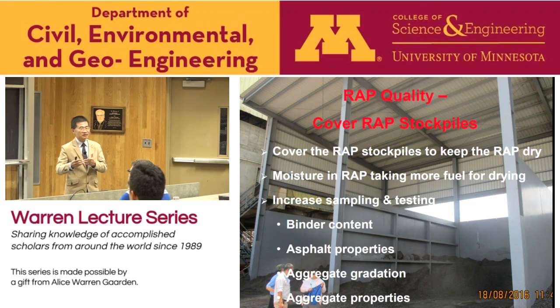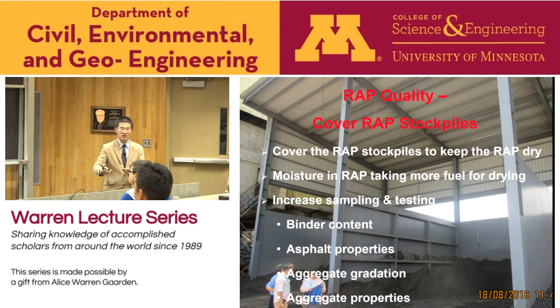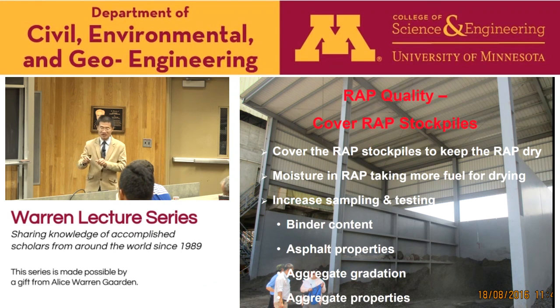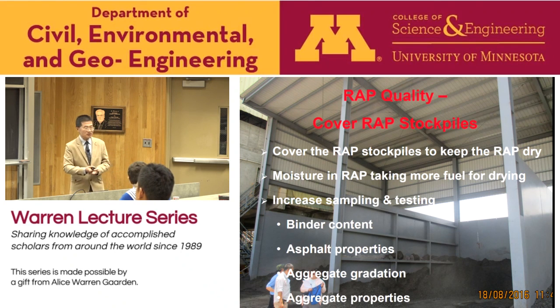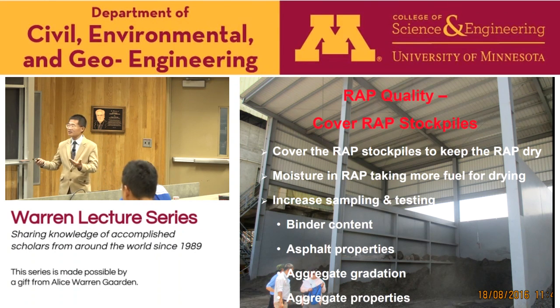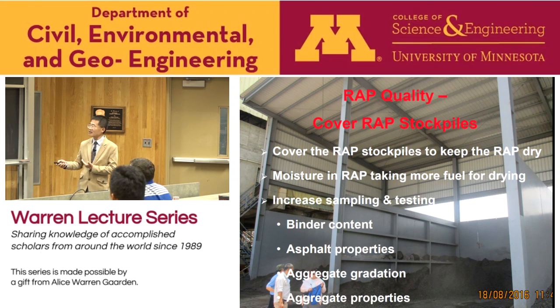In general, it takes 10 liters of fuel per metric ton of aggregate to remove 5% moisture content and heat the asphalt mixture to a mixing temperature of around 160 degrees Celsius. So moisture in RAP will take more fuel for drying the same amount of water. Using a cover here would keep the moisture content of the RAP stockpile below 2%. That's a significant reduction. In addition to the moisture content, it's important to increase sampling and testing frequency to make sure that the quality of RAP is uniform in terms of binder content, asphalt property, aggregate gradation, and aggregate properties.